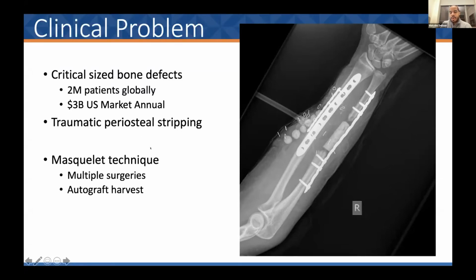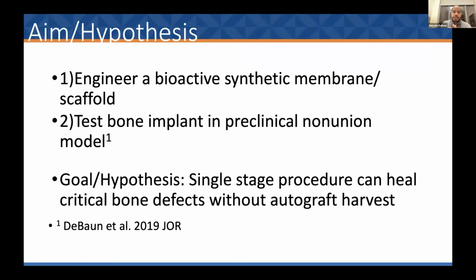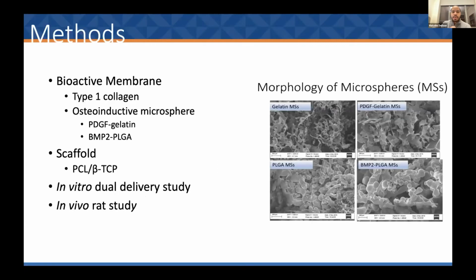Right now, one of the ways that we address this surgically is through the so-called Masquelet technique, but it requires multiple surgeries and it requires autograft harvest, which has significant donor site morbidity to the patient. So what we wanted to try to do is engineer a solution. A bioactive implant that is capable of healing critical bone defects without autograft harvest that can be performed at a single stage procedure. So we developed a preclinical non-union model initially, and then began testing our implant.